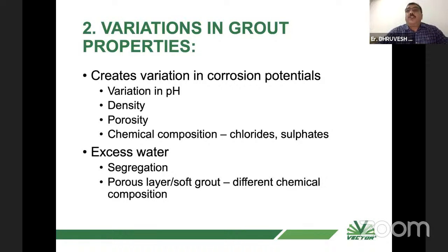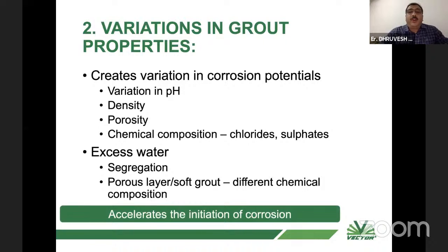And if there is moisture presence of more than 5%, definitely it's going to corrode. There will be corrosion maybe of the top tendons, maybe of the sheath, or maybe of the grout, which is not as dense at the top side if it is on the lower portion of the tendon. And all these reasons accelerate the corrosion.